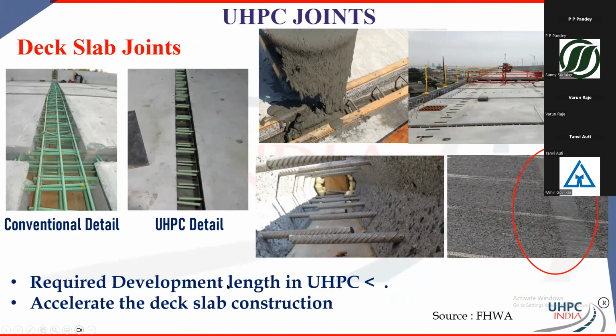typically your development length for rebar in normal concrete is about 40 to 50 times the diameter. With UHPC, you just need less than 1.5 times the diameter, 15 times the diameter. Therefore, UHPC stitches are pretty lean. You can see that over here, extremely lean.